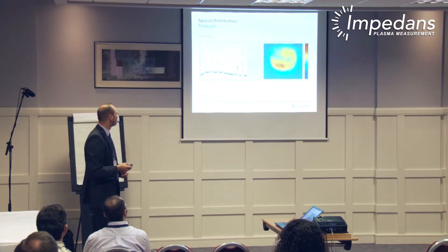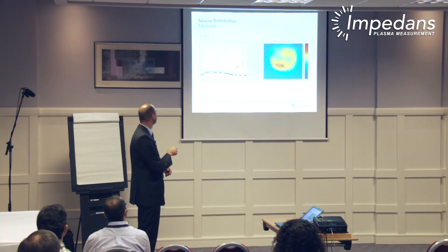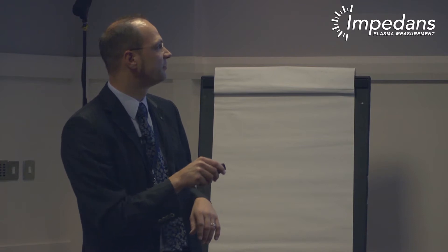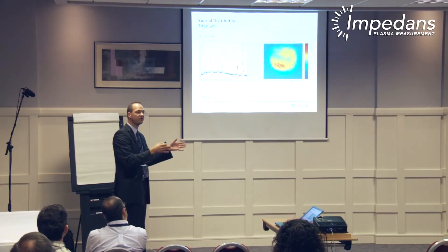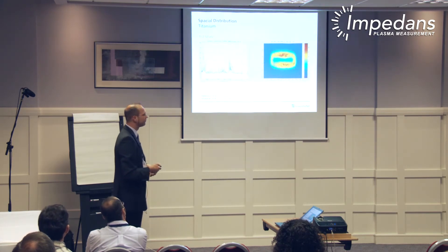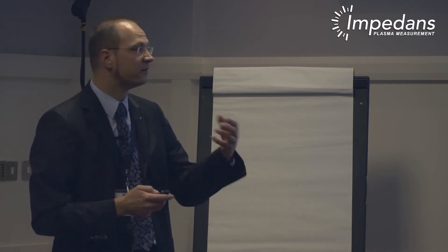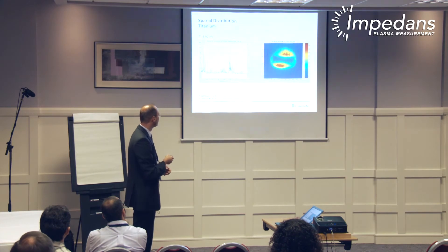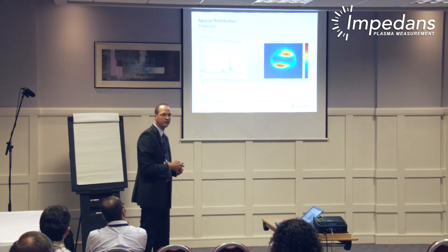There are also some spatial measurements. You can pick up from your optical emission data from specific emission lines a top view of the sputtering cathode and an intensity profile reproducing the racetrack — here the cathode is 500 by 250 millimeters. For neutral argon excitation you see a broad distribution in front of the cathode. For titanium emission it's more focused on the racetrack, and with increasing energy of the transition from the emission line, it gets more and more focused — metal generation is very close to the target in front of the racetrack.